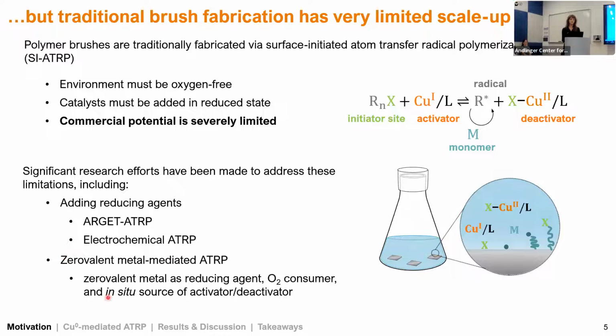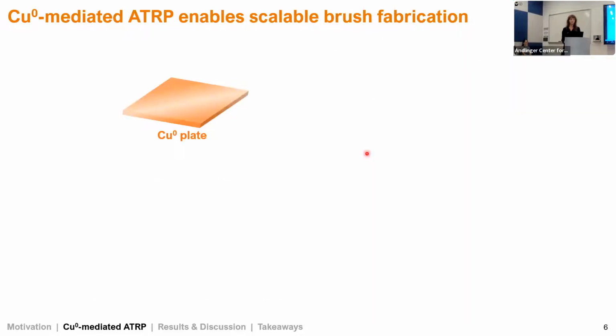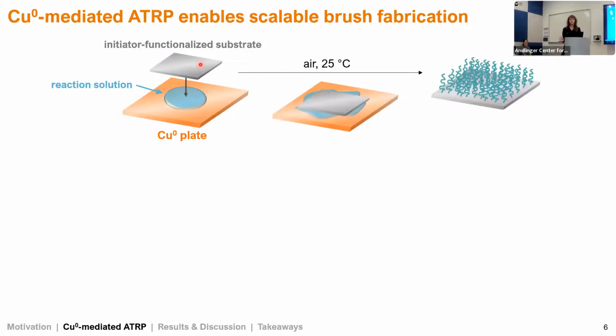So in this scenario, we use a zero valent metal, typically copper, as the reducing agent, as well as the oxygen consumer, and it can act as an in situ source of our activator and our deactivator species, as I will show here. Okay, so in copper-mediated ATRP, we take a copper plate, we bring that into contact with our reaction solution, and we bring that into contact with our initiator functionalized substrate. And if we leave this at ambient conditions for some time, this will result in polymer brush grafting.